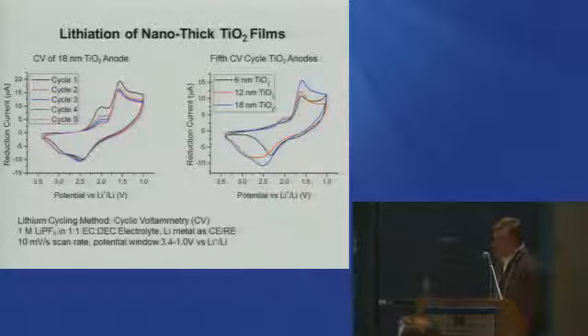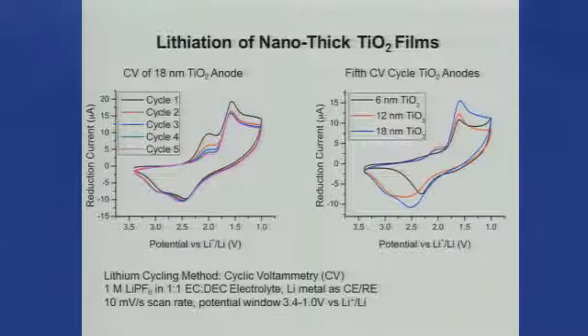Okay, if you cycle these electrodes in the conventional battery electrolyte, lithium hexafluorophosphate in dimethyl and diethyl carbonate, ethylene carbonate type structures, here is an example of some of these electrodes. Here's an 18 nanometer thick TiO2 anode. This is flipped on the scale, I apologize for that. One student plots it by the UT conventions, the others plot it by the battery conventions. But this is the reduction process. And you can see at very high potentials, you see this peak that starts to diminish after consequent cycling, and then you see this kind of stabilization occur.